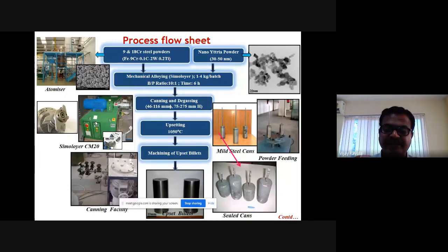But the conventional consolidation process, like press and sinter, like any powder metallurgy process, doesn't work, because this powder has gone through a lot of milling collisions in the mechanical milling process, so they accumulate a lot of strain. Once we have strain in that, then when you are pressing it at room temperature, they will have a spring back. So the green density you get in this material will be very low. And when you do the sintering, you will not get a good density. The density is only around 80%, and the remaining will be porosity.